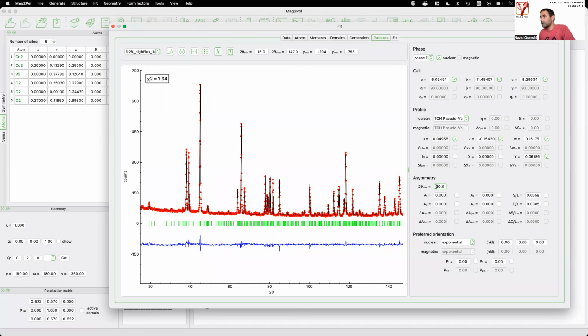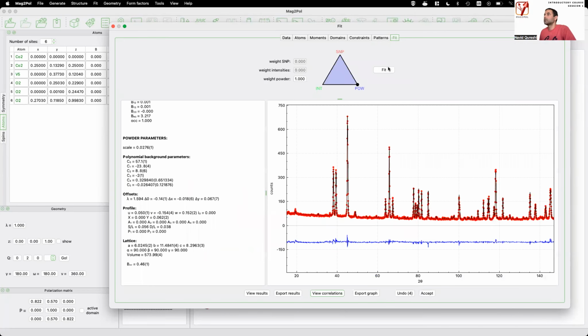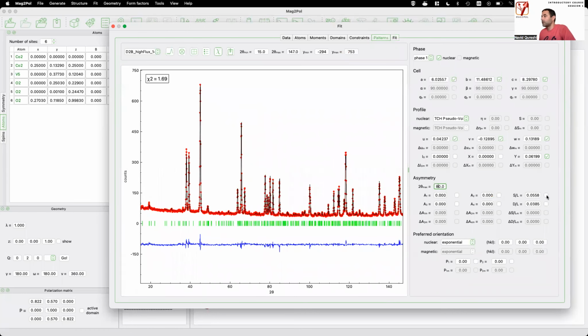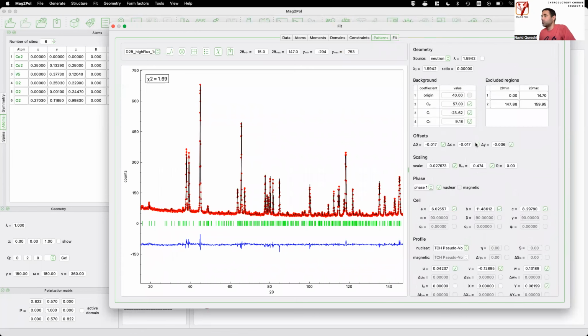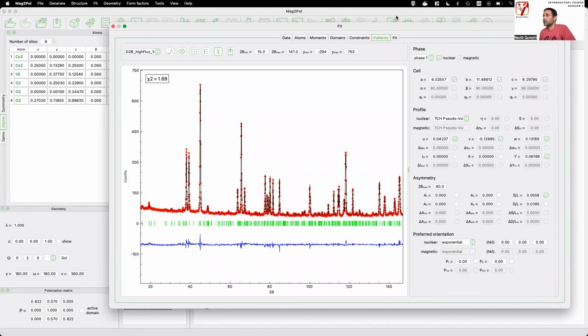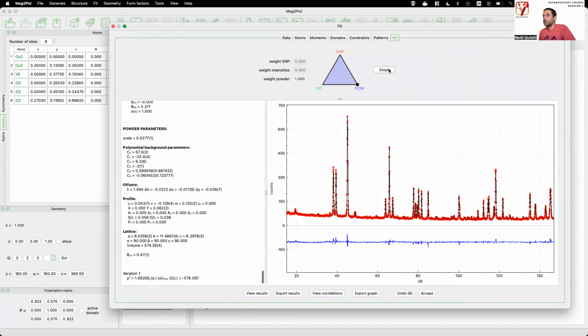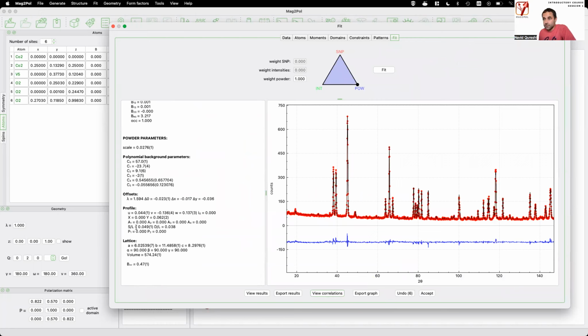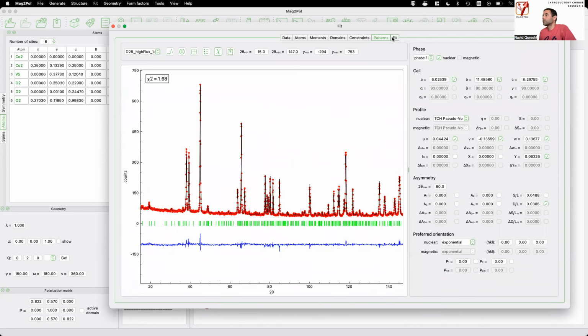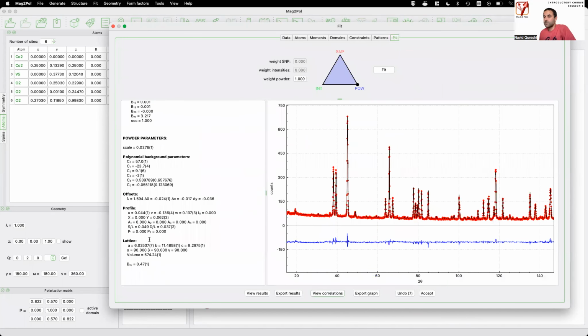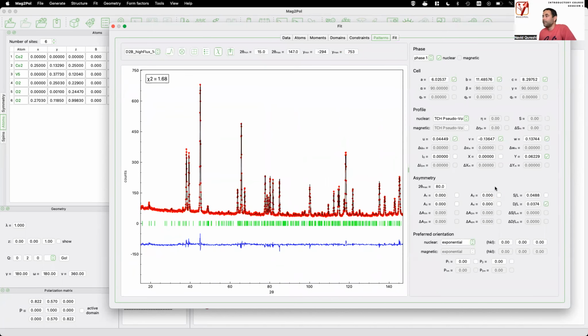So I'll say, please apply the correction up to 80. You see how that already affected those peaks. So I will just run the fit with the same fit flags again. And now I will refine those SL parameters, but I will remove these flags because there is a strong correlation between those parameters for some data. So I fit that, and you can see in the results here, it has a reasonable value with a very significant standard deviation. And you can also fit the other one. So that works like a charm. Okay, so that looks like a success.